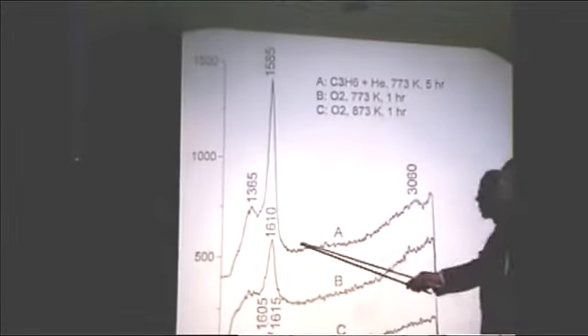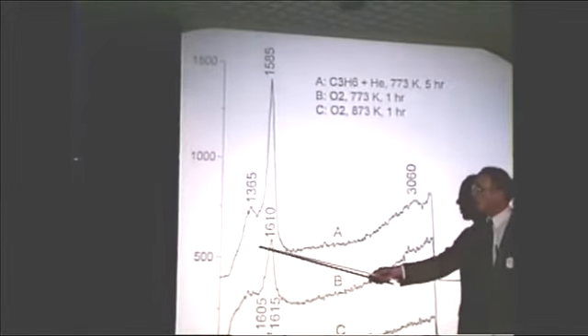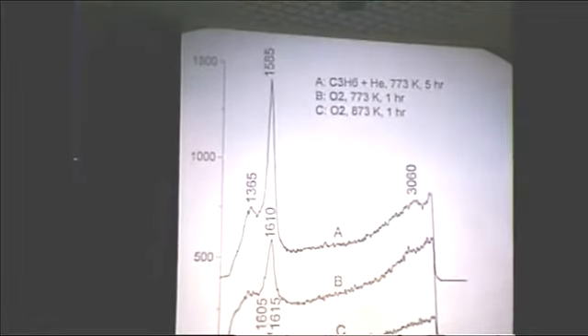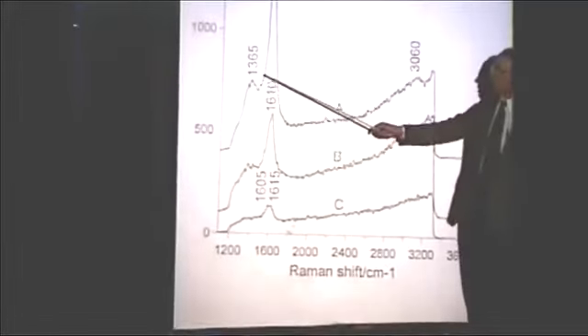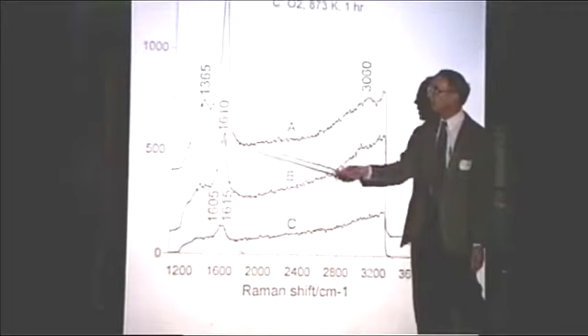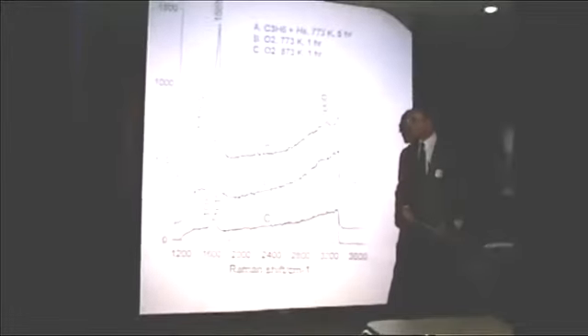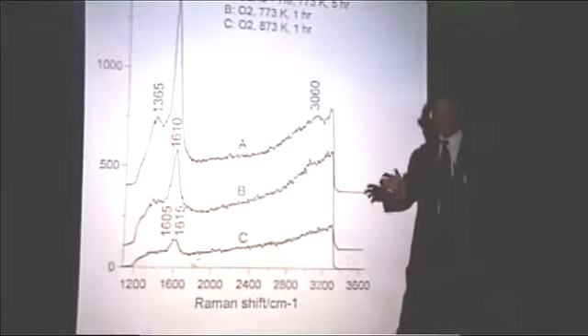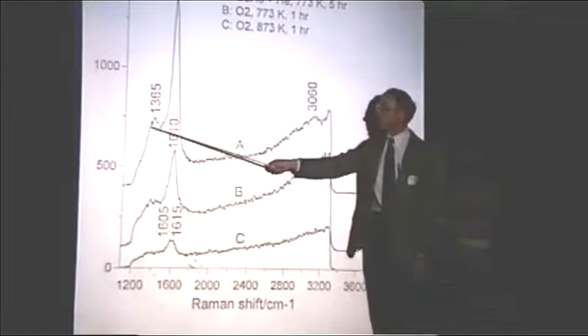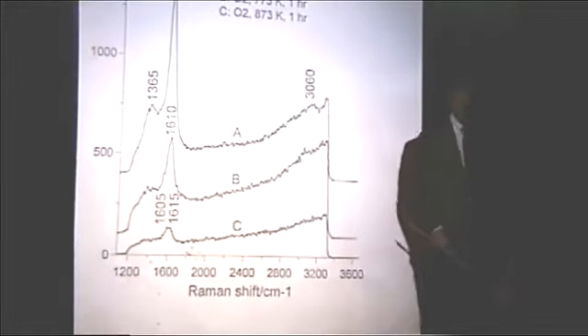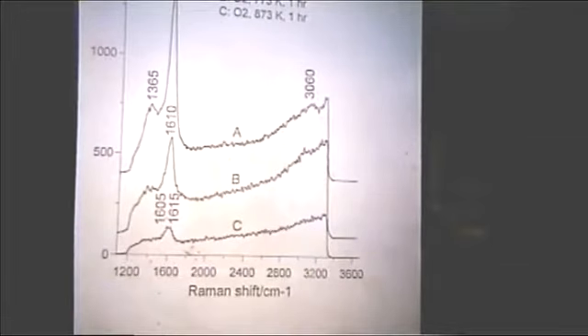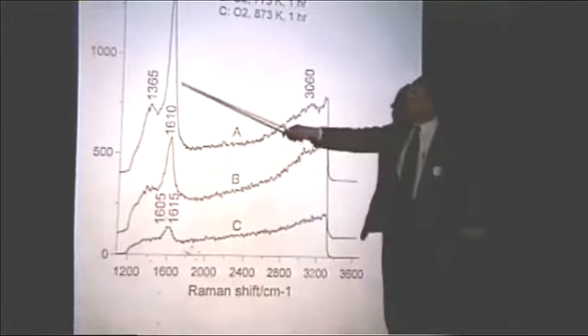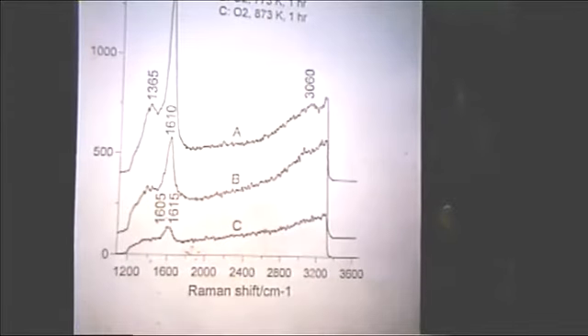And now we get a spectrum here after 5 hours at 500 degrees C, which looks like almost a literature spectrum for microcrystalline graphite, or defective graphite. This band over here at 1365, you might remember that the graphite spectrum was very clean. There was just one peak. This is characteristic of vibrations that are associated with the edges of the graphite planes. And this very strong band then showing up at 1585.